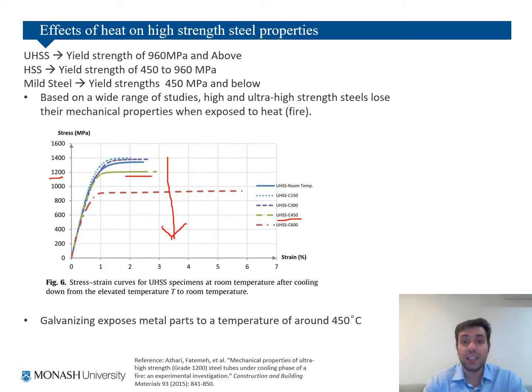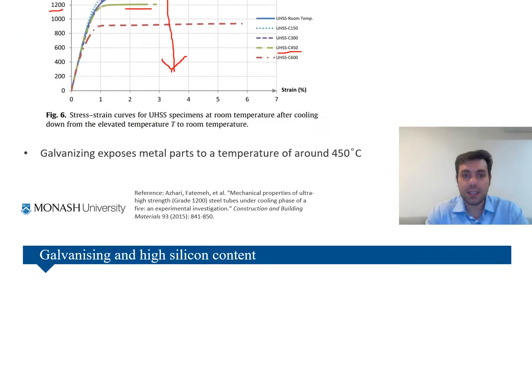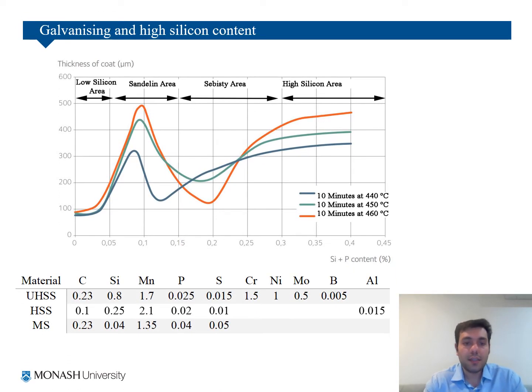The other important thing when it comes to galvanizing of these types of steel is the silicon content. For example, as you can see here for UHSS, HSS, and mild steel, the silicon content is changing a lot, and it is important. As you can see here from this curve from ArcelorMittal, the silicon content is changing the thickness of coating a lot. For example, if the silicon content is above this value, you can see that a big coating thickness can form when they are dipped for 10 minutes in molten zinc.